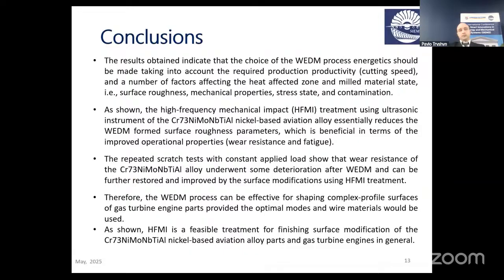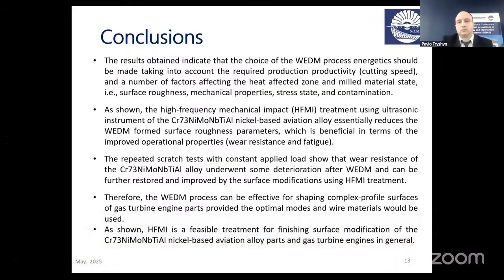So we can conclude the following. The results obtained indicate that the choice of the EDM process should be made taking into account the required productivity and a number of factors affecting the heat affected zone and material state, surface roughness, mechanical properties, stress state, and contamination. High frequency mechanical impact using the ultrasonic instrument essentially reduces the surface roughness, which is beneficial in terms of improved operational properties. Wear resistance can be restored and improved by surface modification.